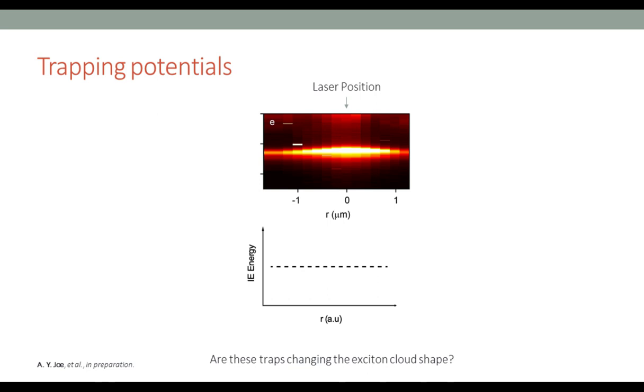And so the measurement here that we're going to do is, instead of only looking at the counts, we can also scan our collection across the outer gate, wire gate, and outer gate again, to see the energetic profile of the interlayer excitons that we're generating. So the first step to controlling and generating these traps is to generate the correct electrostatic profile. First, we check along a line cut across these traps whether we have a uniform energy, which we do. You can see on this scale that this energy is quite flat when we don't apply any electric field.